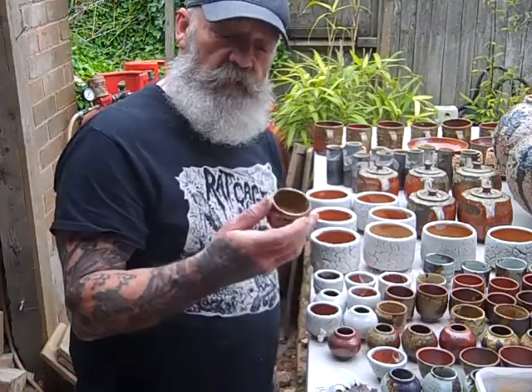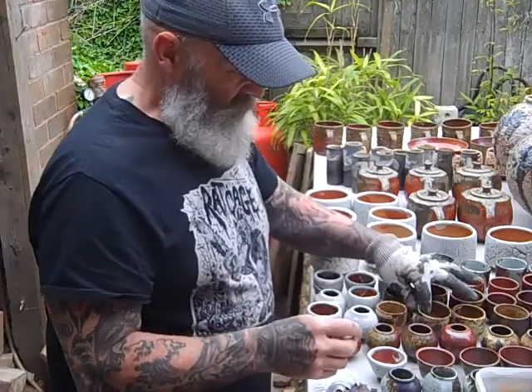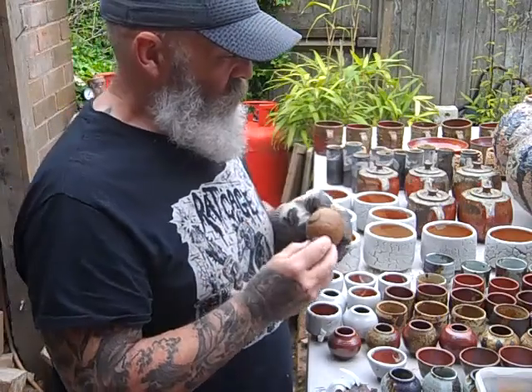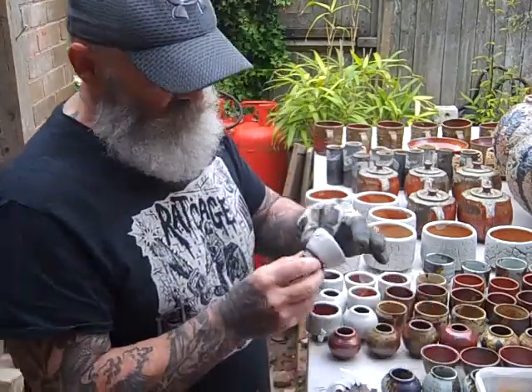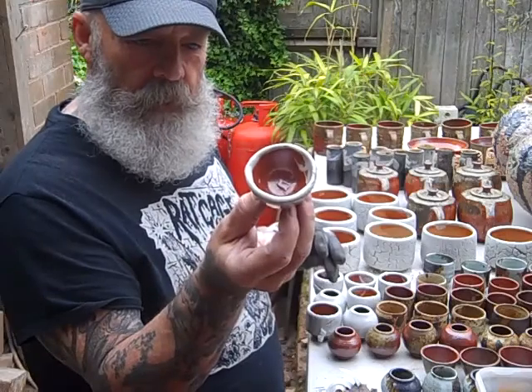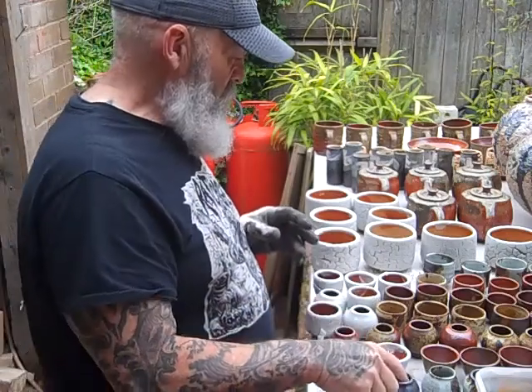Successes. All of the little kiln fillers have come out. This is the dolomite glaze with splashed brushwork on — they come out okay, these always come out okay. These are the shino with the wood ash added, they're okay. Here's some more dolomite glaze with cobalt on. Some little V-shaped ones with the wood ash on — they've come out okay. These were experiments: basically feldspar and 10% clay fired to cone 9, with a shino inside — they've come out okay. And all the little nuka moon jars have come out okay. You can control that, no problem.